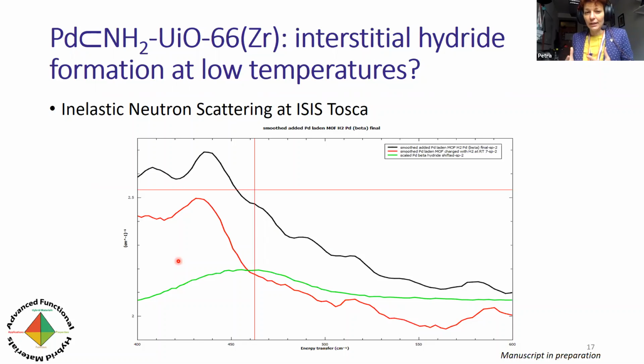spectroscopy. Now, I really don't want to go into a lot of detail. A, this is not what I do on an everyday basis, and B, if I started to talk about this, it would never end. But suffice to say that, of course, neutrons are very sensitive to hydrogen in general, and the hydrogen atoms within the interstitial positions are very different spectroscopically from those of the hydrogen molecule in the gas phase they're in equilibrium with, or even from the hydrogen atoms that are chemisorbed on the surface of the palladium catalyst. So we thought that we should be able to distinguish this and demonstrate its presence if it